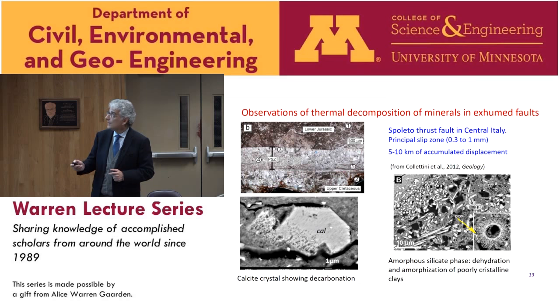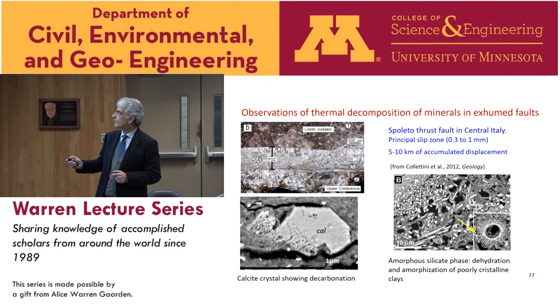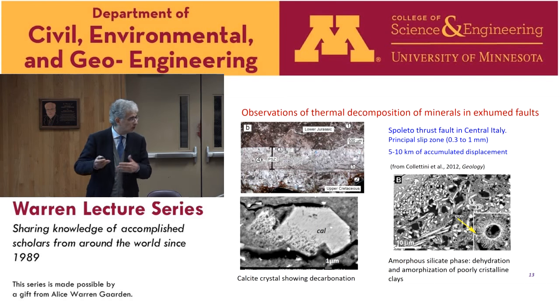But this is also seen in nature, in exhumed faults. It's the same example as before, of the Spoleto thrust fault in central Italy. But now looking in the principal slip zone, we look at what is designated as number 5 here, this very small zone. And the authors have documented, you see this calcite crystal showing decarbonation, these bubbles. Also the fading boundaries here are the results of decarbonation which has occurred during seismic slip. And this is some evidence, with these irregular pores, of dehydration of clayey materials. So it's also seen in exhumed faults.